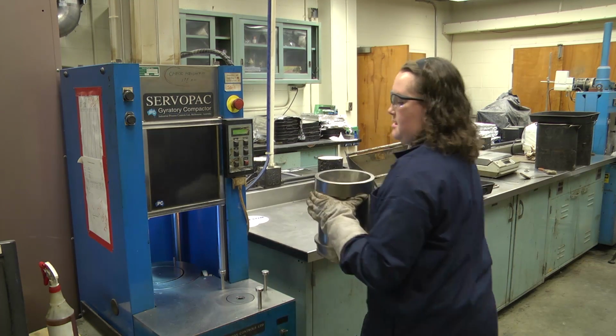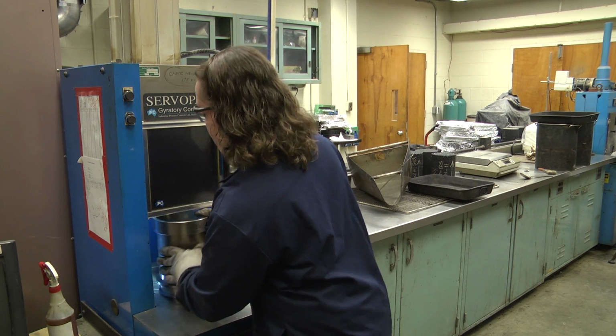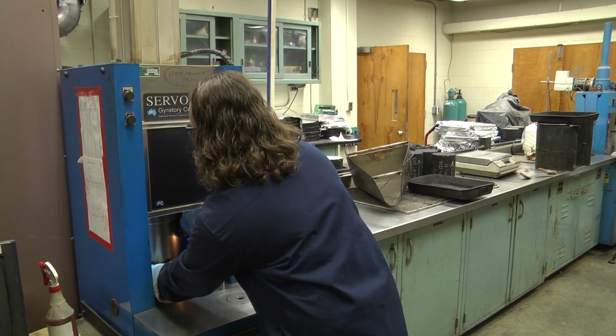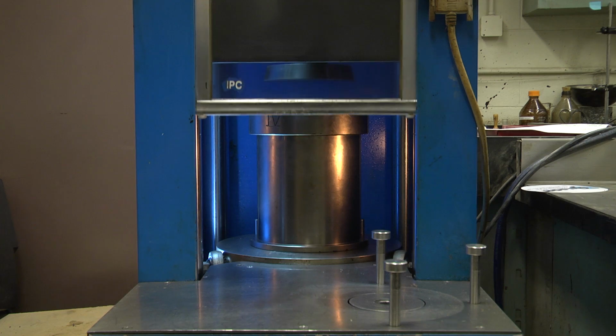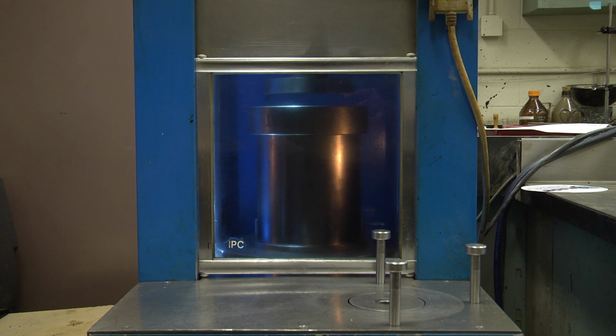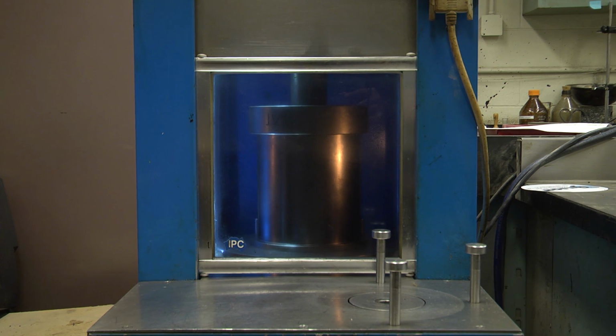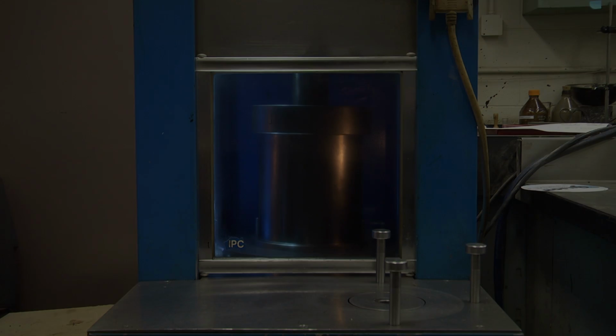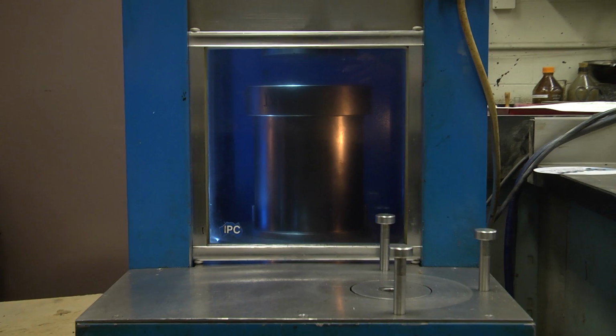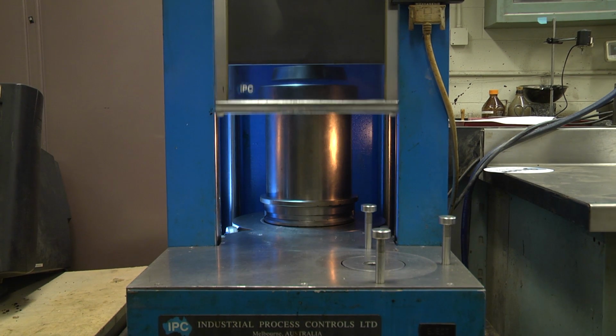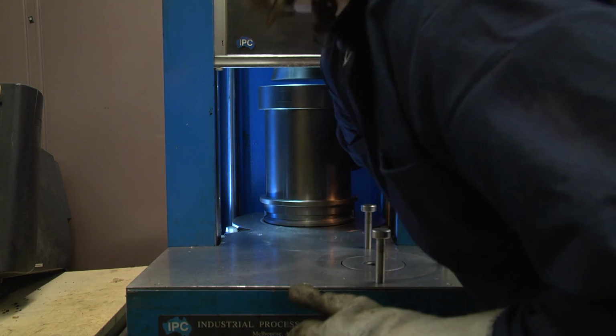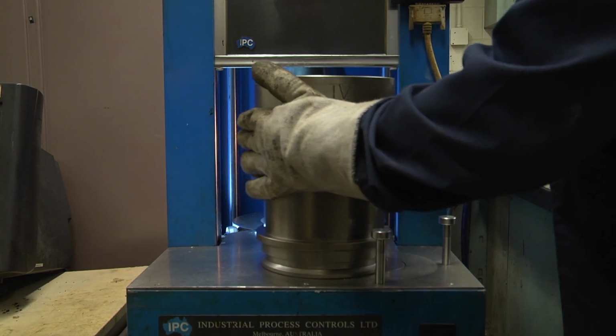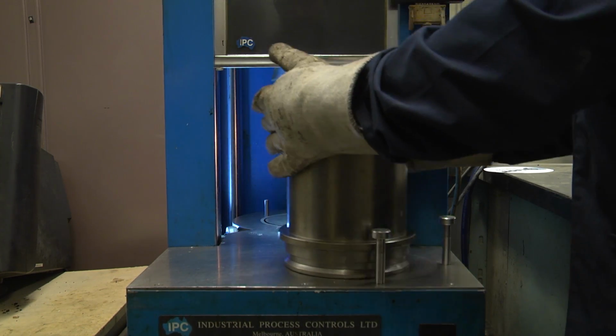Place the mold filled with asphalt mix into the gyratory compactor. Then lock the gyratory mold in place. Begin gyrations and ensure height is recorded as a function of gyration count. The height of the specimen will decrease with gyration count as the specimen densifies. Once the test reaches the maximum number of gyrations, compaction will stop. Remove the gyratory mold from the compactor and use the extruder to remove the compacted sample from the mold.